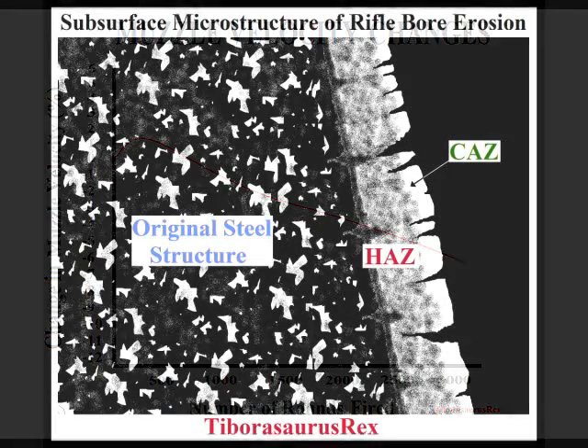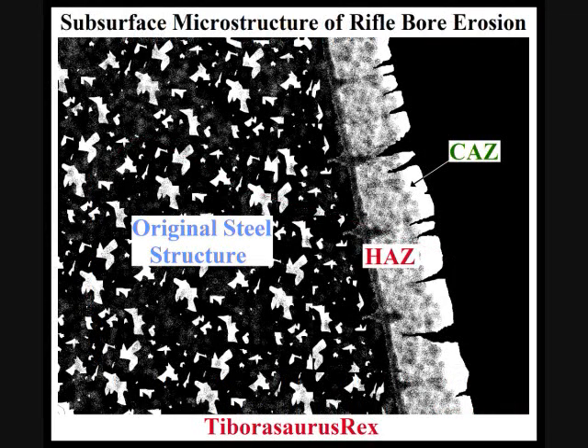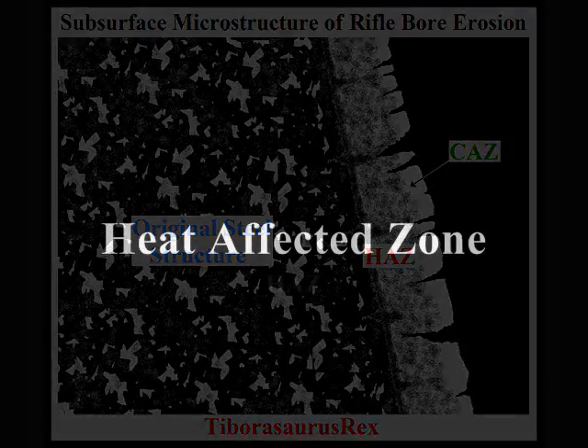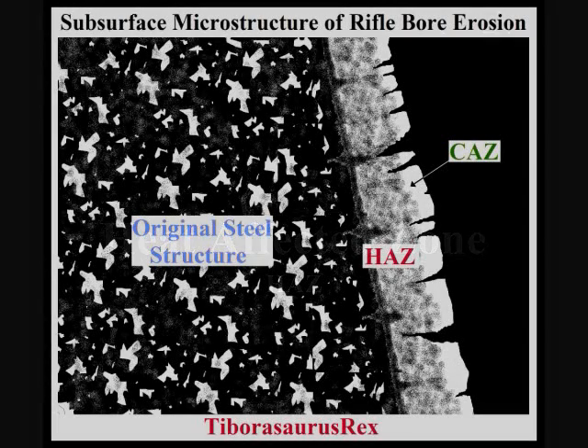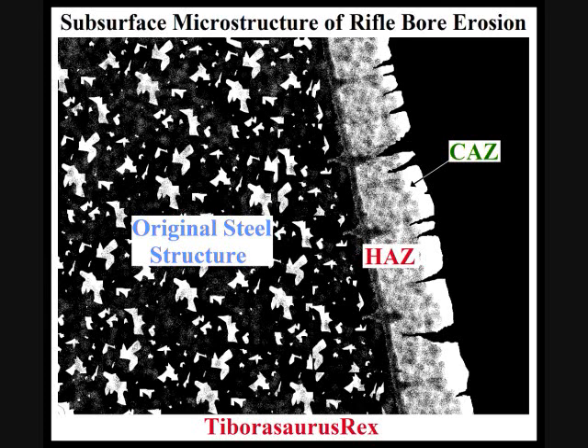So let's look at this here. We got instant temperature increase up to 3,700 degrees Kelvin. Well, basically, at the surface of the bore, that's only going to heat the actual steel up to 1,500 K. So half that, roughly. So you're still going to have a dramatic increase in the steel, but it's not going to be the full 3,700 K. So you're going to have these temperature-affected zones, and they are going to run to a certain depth, and it's going to be a varying depth. And if the surface of your bore is increasing up to 1,500 K, you've got to consider the properties of steel.